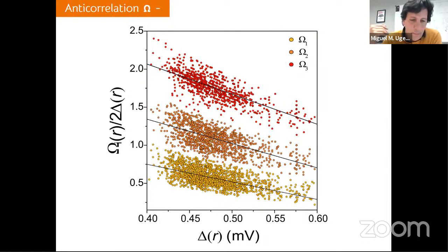The origin could be the presence of edges. We try to do these measurements far from edges and far from dirt clusters. But in the end, you cannot control atomic-size impurities, or the existence of grain boundaries. The position of the edges, even if they are far from the place where you are measuring, probably will have an effect. We are talking about superconductivity, so the coherence lengths that we have to take into account are much larger. So probably all that leads to small modifications of the superconducting order parameter. But in any case, they are not large. They are quite small in general, I think.